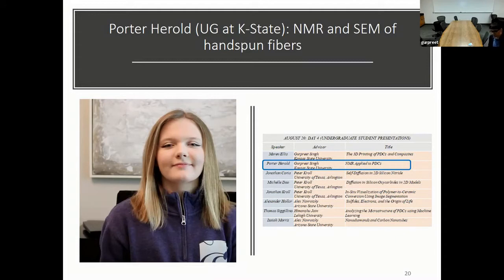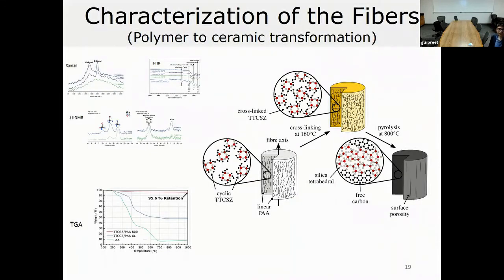But you may notice that this process has problems. One problem, of course, is that we are doing all of this processing in air, which is not a good idea with silazane, because silazane reacts with moisture and produces ammonia, so it's not safe. Also, these ceramic fibers will be carbon rich because of the presence of PAA, which is 48%. And lastly, these fibers are made through hand spinning, which is extremely time consuming.